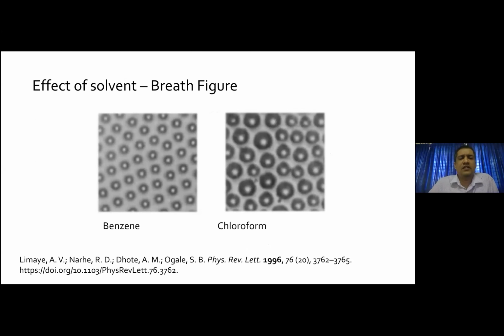The first thorough study on the difference between the solvents was done by Ogale and co-workers. What they did is choose two different solvents, let's say benzene and chloroform. Both of them have almost the same enthalpy of evaporation, so they need the same amount of energy to get into the gaseous form. Because you coat the polymer film in the presence of solvent, and then when you allow gas to flow onto the surface of the polymeric film, because of the flow, the vapors which are close to the surface of the polymer film are swept away, and then new vapors replace them from the surface of the thin film, and because of that evaporation happens, and this cools the surface.